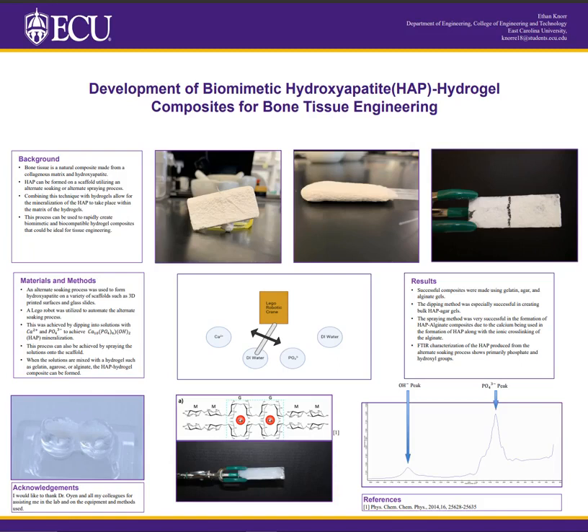For some background, bone tissue is made up of hydroxyapatite, a calcium phosphate mineral, and is set within a collagenous matrix. This hydroxyapatite can be formed utilizing an alternate soaking process. Combining this process with hydrogels gives us the ability to create extremely biocompatible hydroxyapatite composites that allow the mineral to subside in the natural gel matrix. This process can be performed on many different scaffolds, including 3D printed surfaces and glass slides.